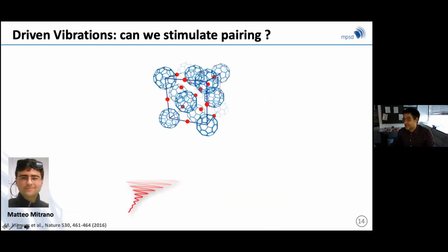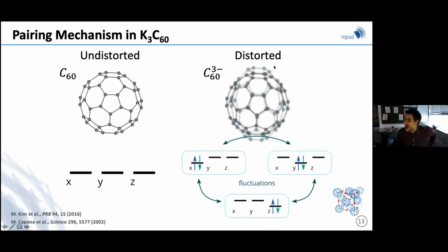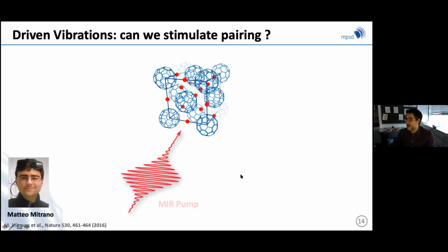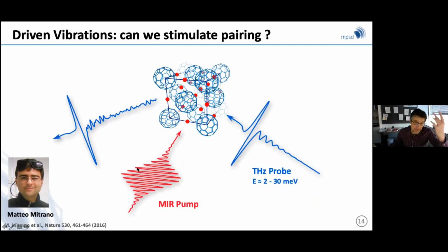And so the idea was now to take a mid-infrared pump pulse, which is resonant not with the Jahn-Teller distortion, but with another vibration that then couples to the Jahn-Teller distortion. This would require too much detail for me, but it is something that is related to this pairing vibration. And so what Matteo thought was, maybe if I shake it right at high temperatures, and then I use a second pulse to interrogate and look for the opening of a superconducting gap, I might be able to see these features reproduced or reduced or changed in an interesting way.